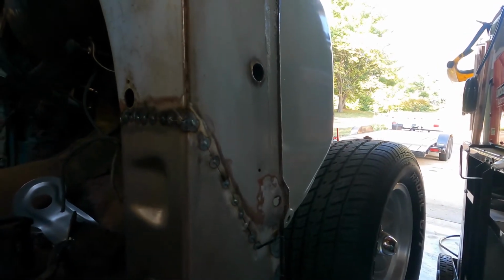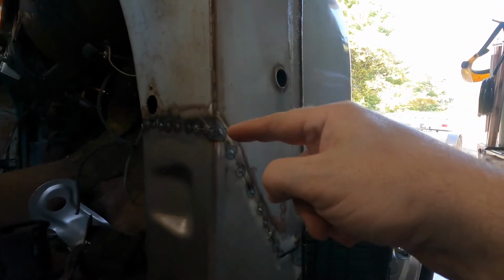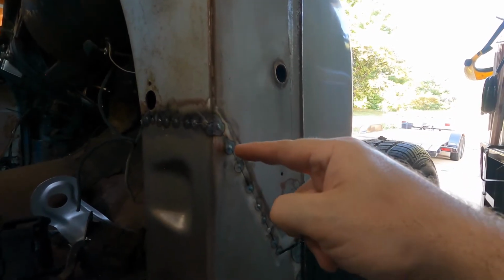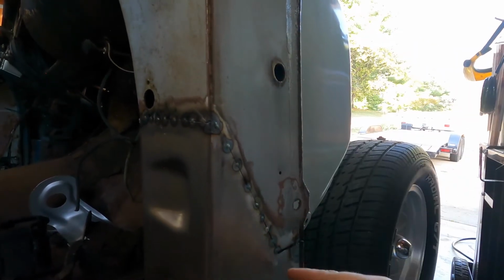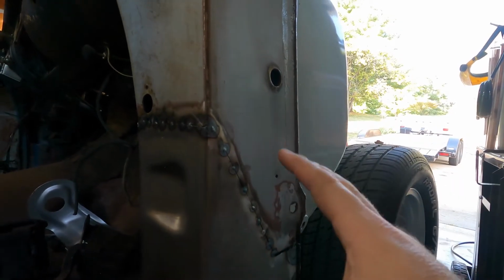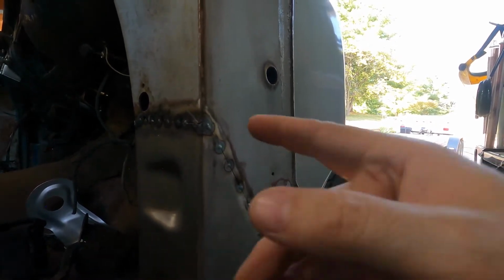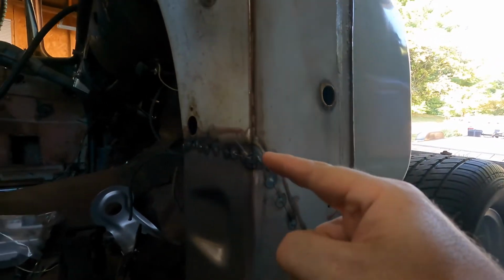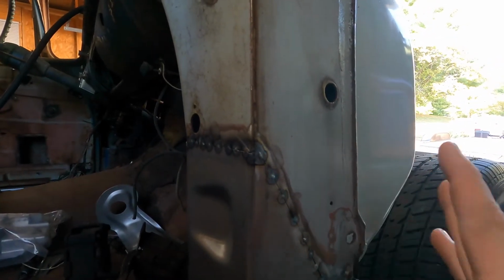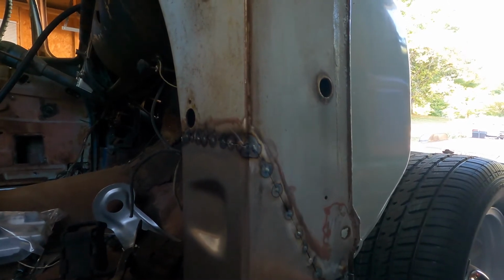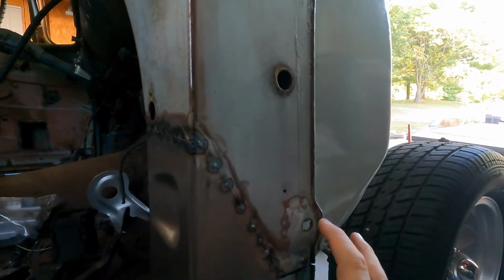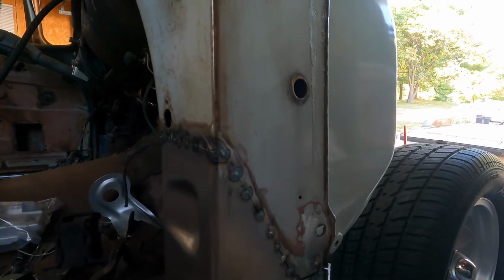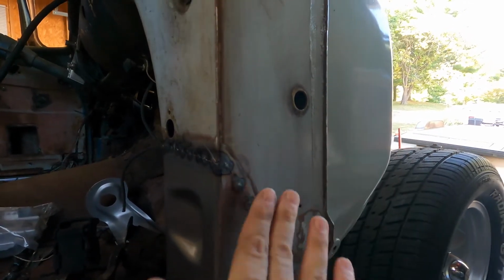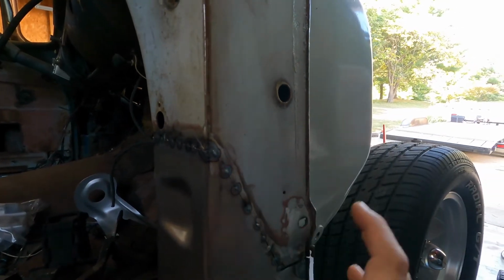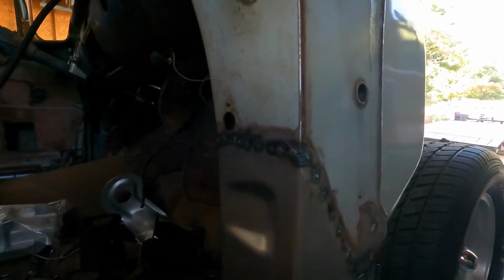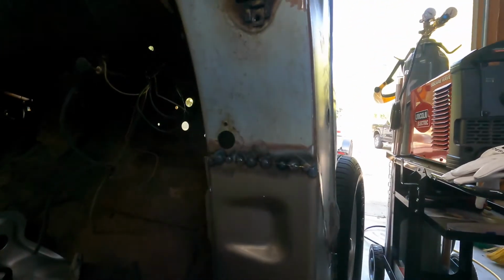I don't know if you've ever done it, but if you run a tack and just go tack, tack, tack, tack in a line starting from one side on something that you're wanting to maintain a gap, you'll notice that as the tacks start shrinking, the right end here, say if I was going left to right, would be completely closed up, even if I started with a gap, and even if I had it all clamped up, because it's sucking together. So that's why you peen them, to relieve the internal stresses.